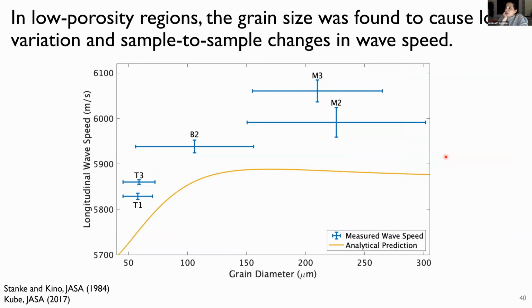So we went ahead and represented Stanke and Kino's unified theories for scattering in polycrystals. So we did the wave speed as a function of that grain diameter. And although the error bars are large, expectedly, because we have a distribution of those grain sizes, we see that the change in the wave speed that we're seeing across the samples is dominated by that change in the grain diameter. So porosity is not playing as big of a role because we're talking about less than 5%, and the variations that we're seeing in the grain size are rather significant.